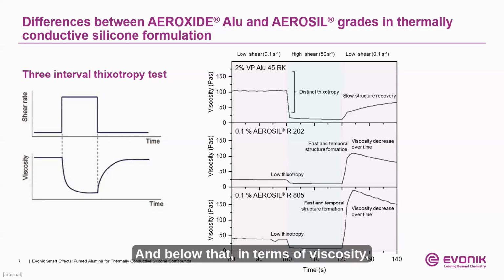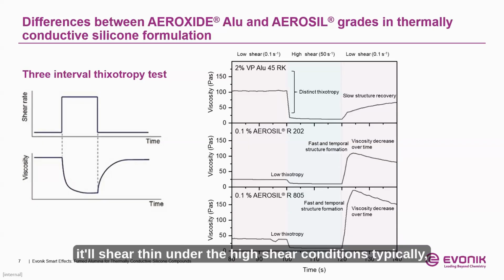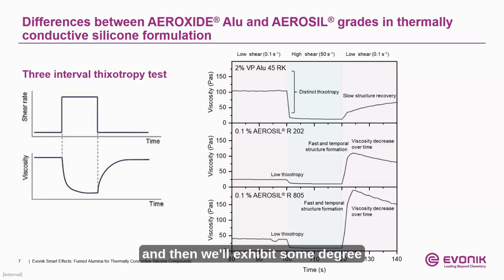And below that, in terms of viscosity, you can see the viscoelastic behavior of the materials. It'll establish a baseline. It'll shear thin under the high shear conditions typically, and then will exhibit some degree of post-shear recovery when exposed to the low shear conditions following the high shear rate testing. The images to the right show the practical application of this testing, evaluating one sample of fumed alumina versus various fumed silica grades. Here with the 2% VP-Alu45RK, the topmost image, we observe a distinct thixotropic nature of the product at rest.